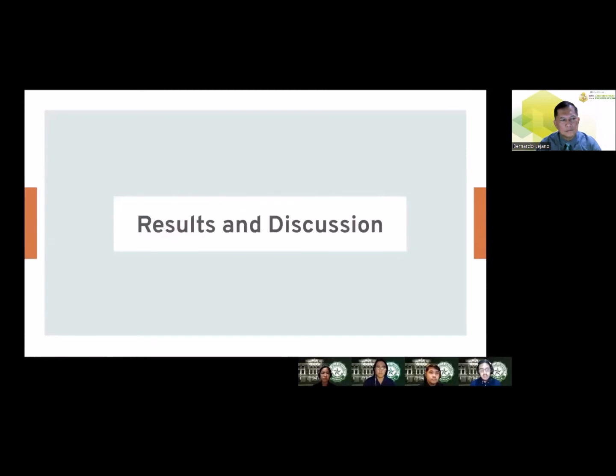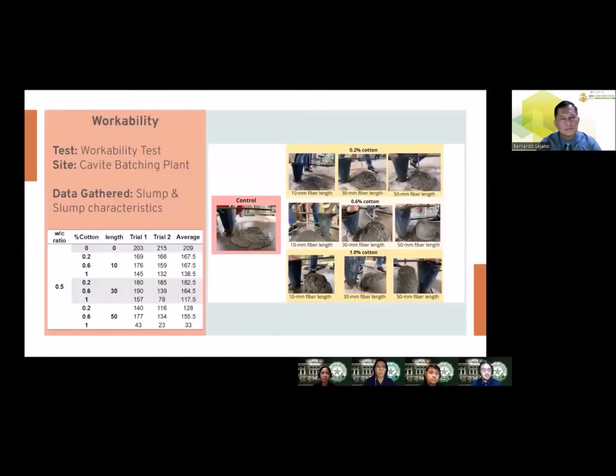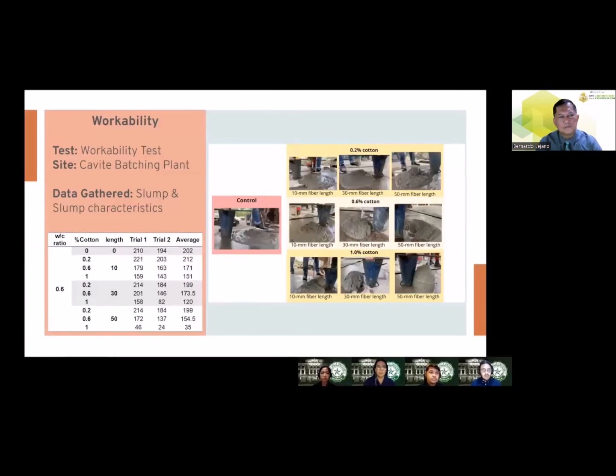For our results and discussion, the first set of results include the results from the workability test. The data that were gathered were the slump and the slump characteristics, and the table above shows the results for the water to cement ratio of 0.5 with varying amounts of cotton fiber. Now, the second set of results are the workability results of the water to cement ratio of 0.6 with varying amounts of cotton and fiber lengths. For each case, based on the independent variables, 2 trials were conducted and the average was obtained.